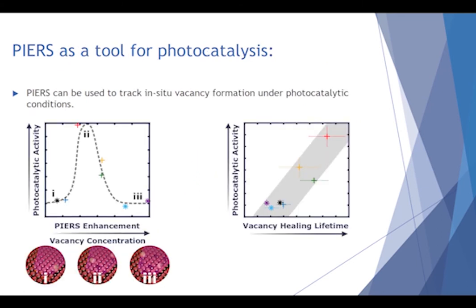In this work, we use PIERS as a tool to probe photocatalytic particles under reaction conditions to track the formation and healing of oxygen vacancies. We found that the concentration of vacancies does not directly correlate with the photocatalytic activity of the film. However, a Goldilocks concentration can be found for ideal photocatalytic efficiency. In addition, longer-lived vacancies appeared to correlate with higher photocatalytic activity.